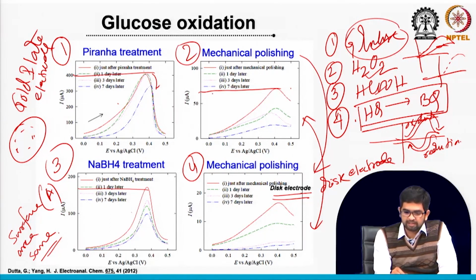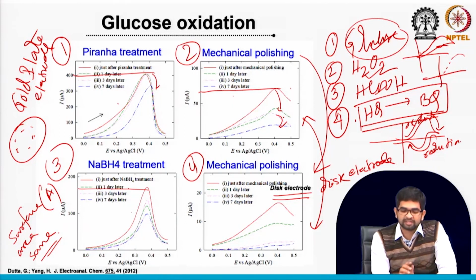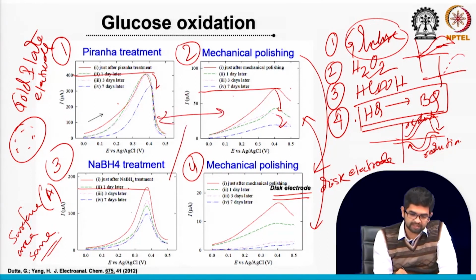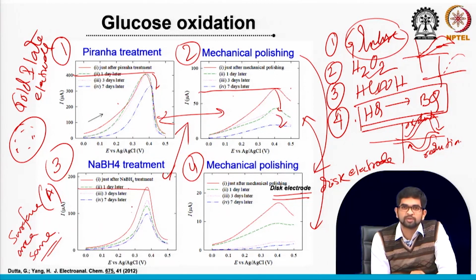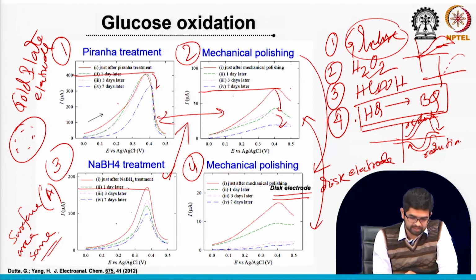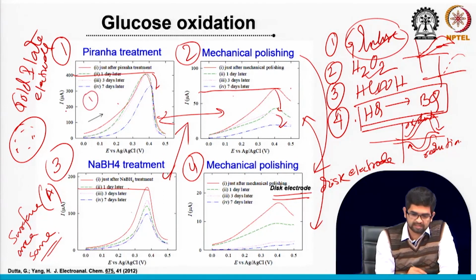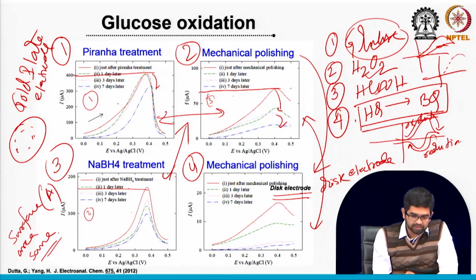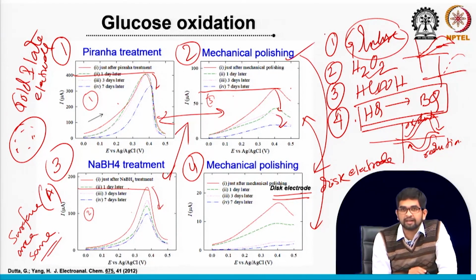See, in the mechanical treatment case, the surface area is the same, but it is not that much activated, and deactivation is also rapid. It means the surface was not cleaned properly, and that is affecting your surface deactivation too. So this is a very interesting phenomenon, right? These are two observations. Again, you can compare with the third condition, the sodium borohydride treatment. Just after sodium borohydride treatment, we can see the glucose oxidation peak around 180. So it is medium: this one is the highest, then this one second, and this one third, if you compare the activation rate. The sodium borohydride case also deactivated, but not as rapidly as the mechanical.